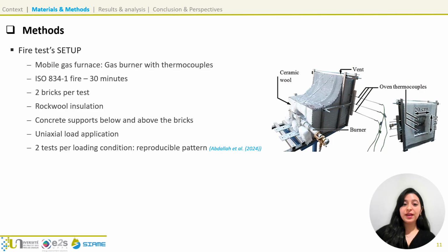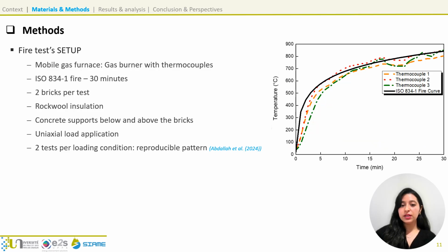To study the fire behavior of the bricks, we set up a controlled experiment using a mobile gas furnace. It is equipped with a gas burner and thermocouples, and we followed the ISO 834-1 fire curve for 30 minutes. As shown in the graph, the measured temperature closely follows the standard curve.